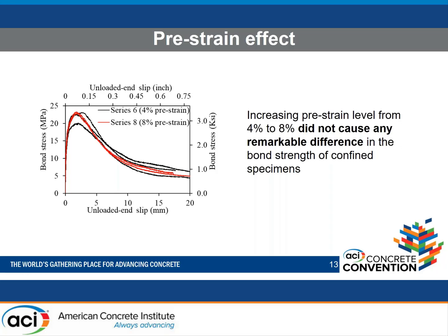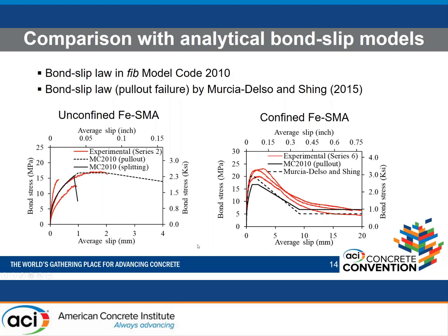After comparing the shape memory alloy bars to the conventional steel bars, and after we found out that they are very similar, we decided to compare those bond behavior profiles to available models, and we chose two models: the commonly used FIB model 2010, which has both pull-out and splitting plots or models, and another more recently developed model by Murcia-Delso and Shing, which was developed specifically for pull-out failure. As we see for the unconfined case, the models are doing a very good job in predicting the maximum bond of SMA bars, and we are presenting here SMA bars with 160 degree Celsius heat activation, which will probably be used when those bars are used.